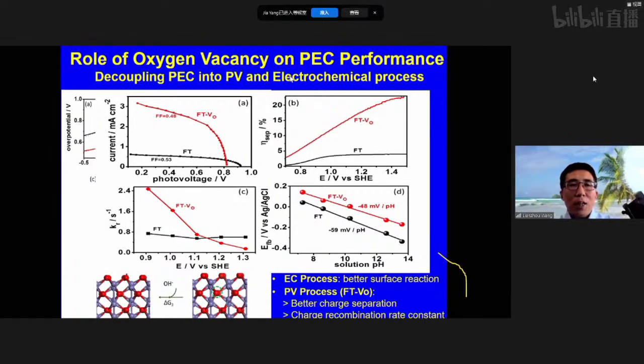If you look at the photocurrent generated on the electrode containing oxygen vacancies, it certainly has a high photocurrent, but the VOC, the open circuit voltage, has decreased compared with the electrode without oxygen vacancy.